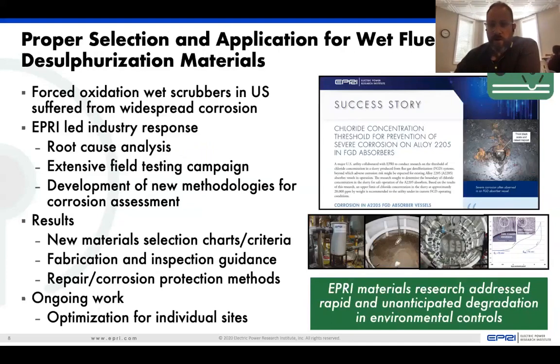Finally, another area that the U.S. has experienced is we've had a rapid growth in the use of forced oxidation wet scrubber technology. And in following this talk, we'll have my colleague Tony Facchiano talk about that in more general terms for emissions controls. But one of the challenges that the U.S. and North America faced when they implemented FGD vessels was the materials of selection. Quite frankly, they did a very poor job of selecting materials, and because of that, we had widespread corrosion issues in our FGD fleet. Over 160 FGDs stalled in only a period of less than 10 years.